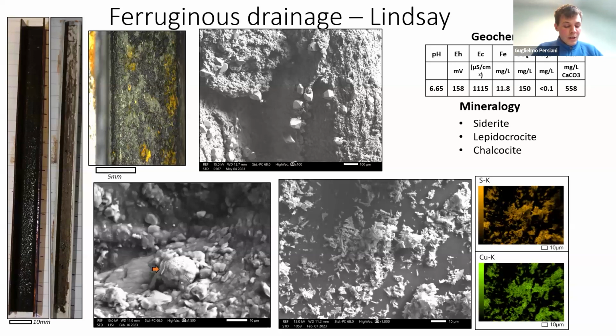And then we pass through Lindsay, which is still an iron site. But here the concentration of iron is much lower, between 10 and 12 milligrams per liter, while the alkalinity is a bit higher. On this site, we did find traces of corrosion, especially on copper, where the corrosion after 10 months appears as a black thin slime on the copper surface, and this mineral is identified as chalcocite.